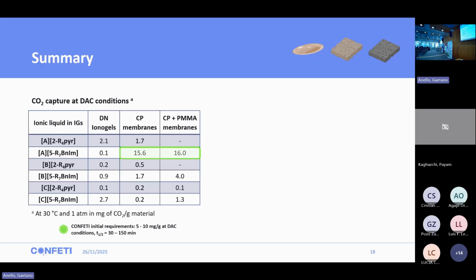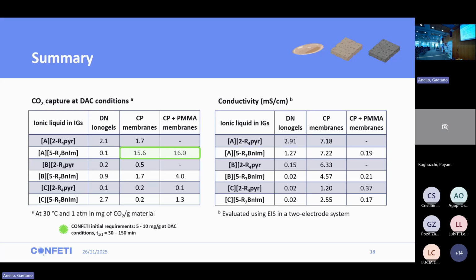And for the future application, we also tested the conductivity of these materials to see if we can use them as electrodes or electrolytes. And what you can see is that the ones with the carbon paper have the higher conductivities, and when we introduce some type of polymers, this conductivity is reduced.